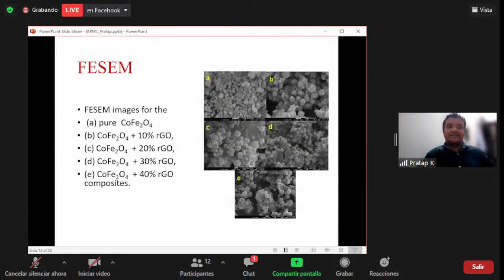Now these are our SEM images. If you look into the SEM images, this is pure cobalt ferrite, then 10% RGO with cobalt ferrite, 20% RGO with cobalt ferrite, 30% RGO with cobalt ferrite, and 40% RGO with cobalt ferrite. You can see that they are spherical particles, anchored onto the graphene layer. So this is the graphene layer, you can see.